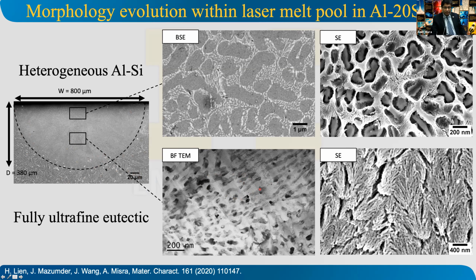One that looks like a two-phase where you have the silicon fiber-looking morphology, and that scale is now 200 nanometer. So you get about 50 nanometer fibers, very fine scale, and also different shape. And you get this other kind where you have these aluminum dendrites, and the remaining structure is the eutectic.